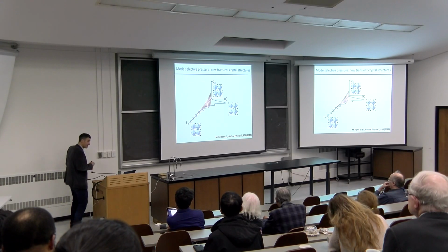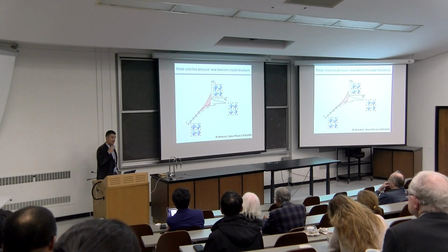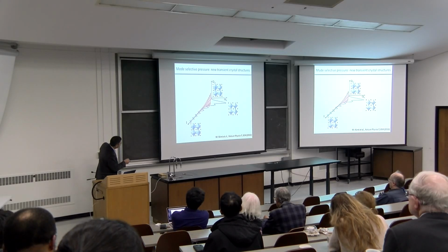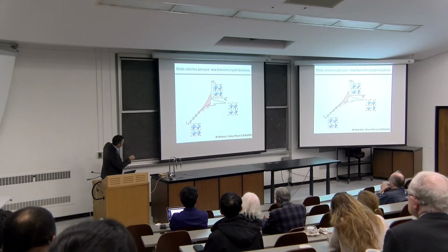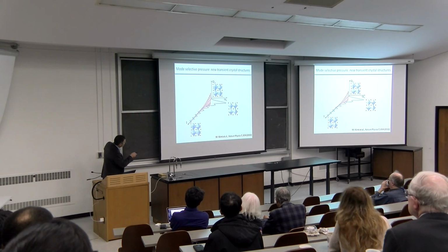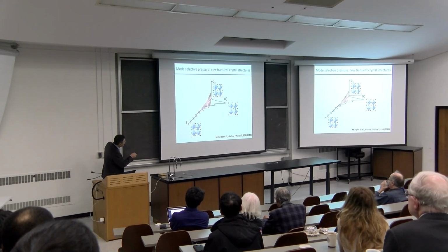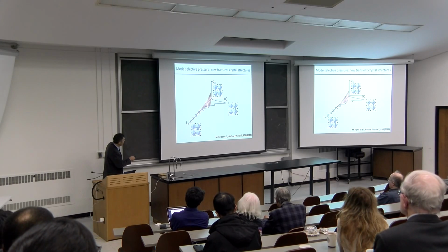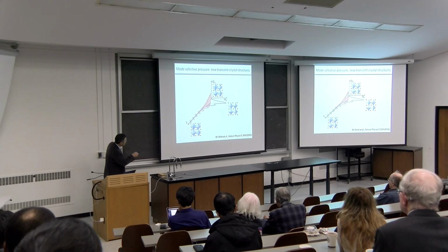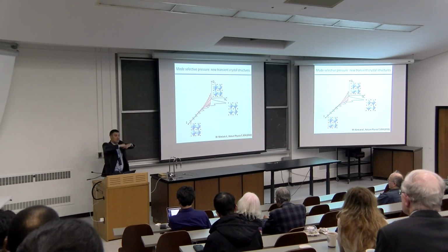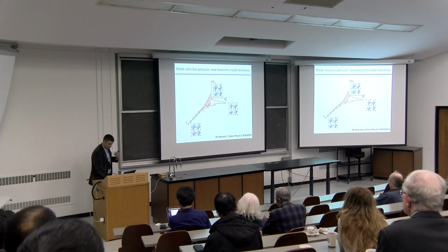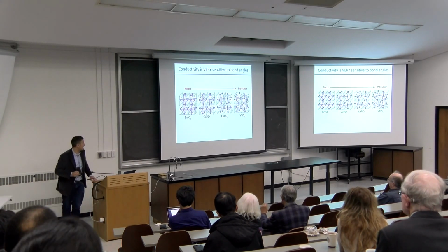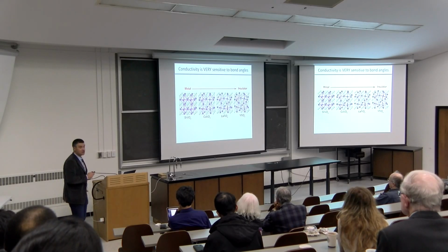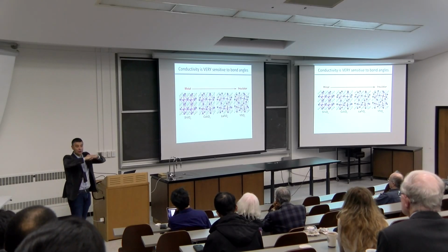Now, I will not belabor this too much. I want to get to a couple of things that are more interesting. We've worked a lot on this, but there's many things that one can do if I take a structure. For example, this is some oxide structure in which the bonds are tilted. And in principle, by doing the right phononics, I can create transiently the same structure, but I can tilt it straight without changing the volume. For example, in some of these oxides, the properties change enormously if I change an angle a little bit.